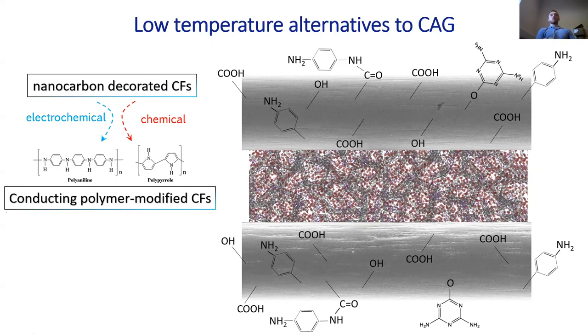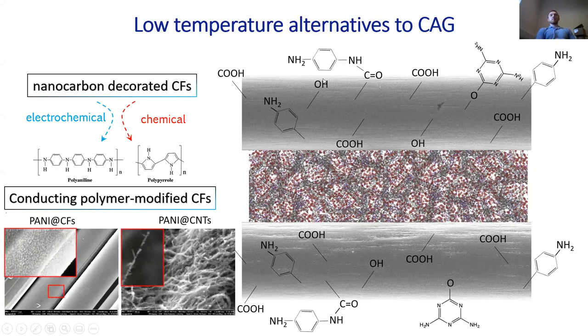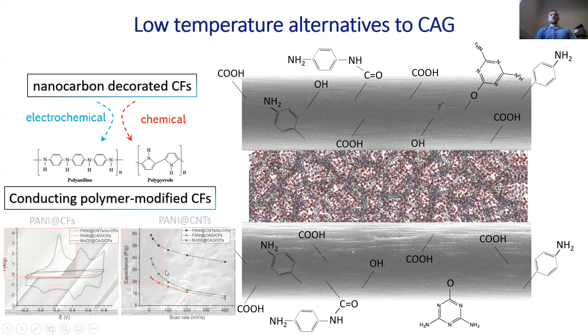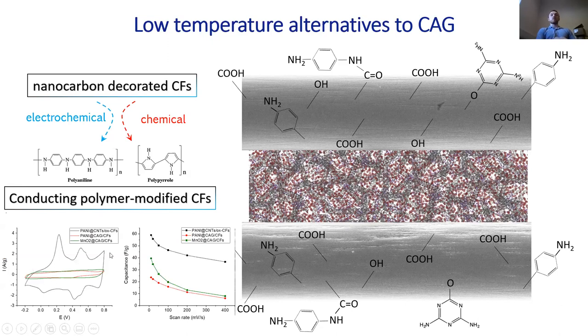So polyaniline was the first target in this direction, and the deposition of polyaniline on top of our nanocarbon decorated functionalized carbon fiber showed that we can achieve a very thin and uniform coating of polyaniline on top of the carbon fibers, as well as on top of the CNT, forming such a hairy structure. This results in significant increase of the performance, for example, compared to the same way deposited polyaniline on top of the carbon aerogel carbon fibers, or the previously shown manganese oxide decoration route, which translates into more than the double increase of capacitance of our material.